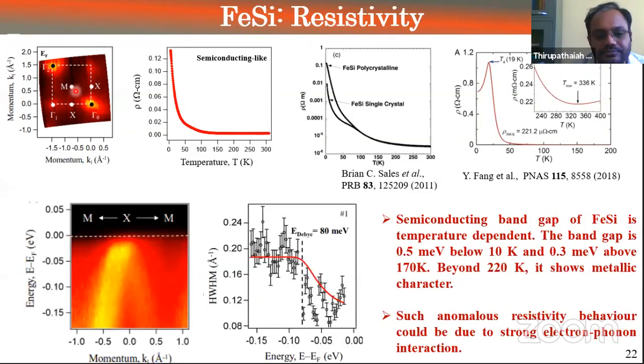Okay, and then there were some papers discussing that electron-phonon coupling could be the reason for this. Since ARPES is a very good technique to identify any such coupling, we immediately started analyzing spectral weights for this band. This is the spectral weight plotted as a function of binding energy, which indeed shows electron-phonon behavior. We fit using the Eliashberg spectral function with the inclusion of the Debye model, which gave us a Debye energy of 80 meV. That is in good agreement with other phonon calculations on this system. Although we don't know exactly, we also know that iron silicide is one of the early systems for which Moriya gave the famous theory of spin fluctuation.